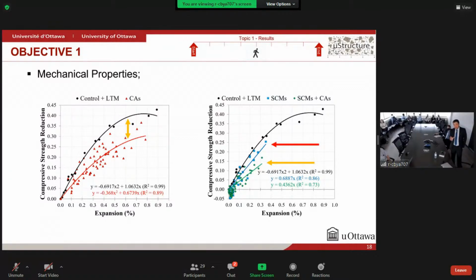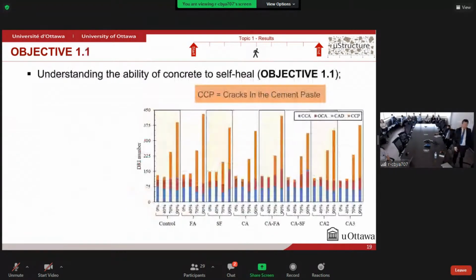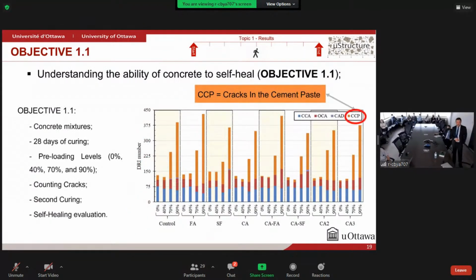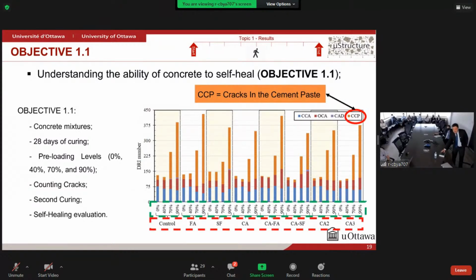So to explain all this behavior, let's stop a little bit and use the results from the parallel research we made. First, to understand the ability of concrete to self-heal, we developed different concrete mixtures. After 28 days, we preloaded them up to 90% of the failure load. And then after preloading the specimens, we tested for DRI. As we can see, increasing the preloading level, we have an increase in the amount of cracks, especially in the cement paste, as indicated here in this orange chart.